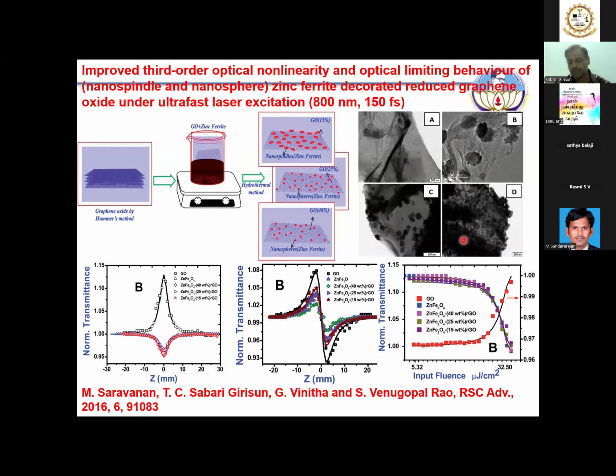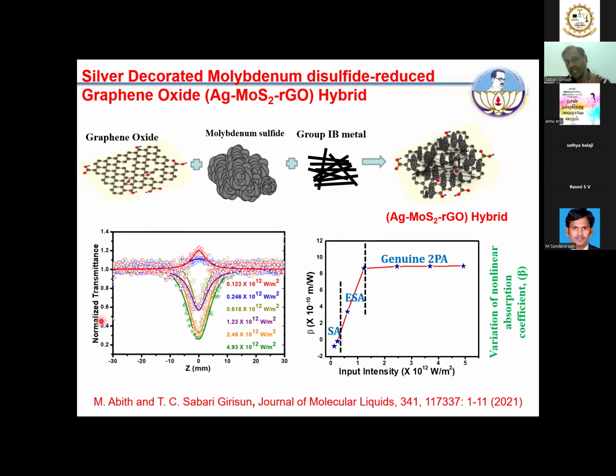Impressed by this result, we performed many experiments on this system. Before I go to another example, I will give you one more example. What we developed in our laboratory was a silver-decorated molybdenum disulfide upon a reduced graphene oxide system. So this is graphene upon which I place microspheres of MoS2 decorated with silver nanoparticles. What we observed in this material, when we performed the Z-scan experiment at different laser intensities with different laser pulses, is that initially the material showed saturable absorbing character. And when the pulse energy was increased and a Z-scan was performed, the material turned into reverse saturable absorption. When we made a detailed investigation of that system, we observed that this reverse saturable absorption arises through a phenomenon called two-photon absorption.